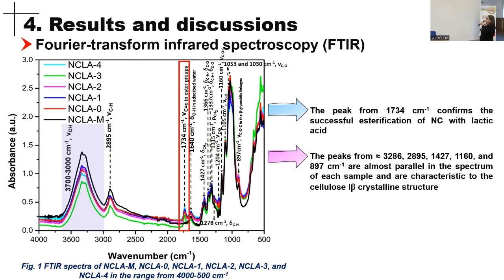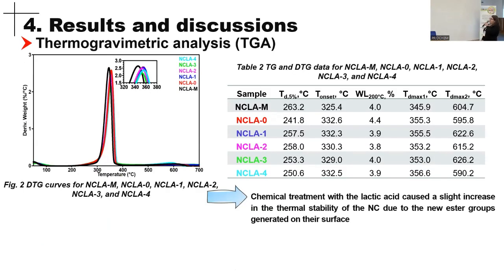However, this peak is completely absent in the case of the control sample, the curve in black, due to the absence of the lactic acid from the acid medium. The thermogravimetric analysis showed that the chemical treatment with lactic acid followed by a microfluidization led in fact to an increase in the thermostability of nanocellulose, which can be seen by the increase in the temperature at the maximum degradation rate and in the temperature of the degradation onset.